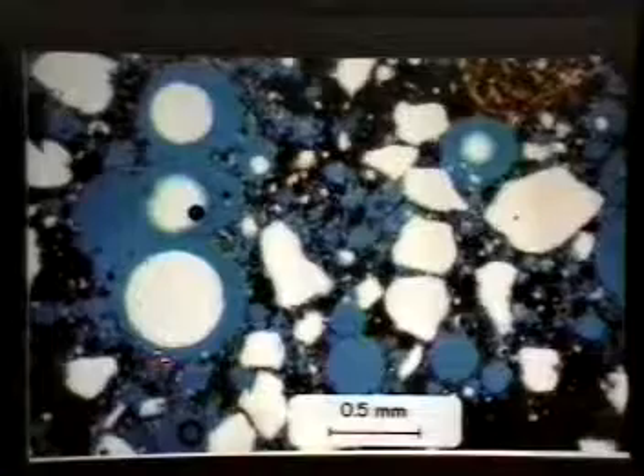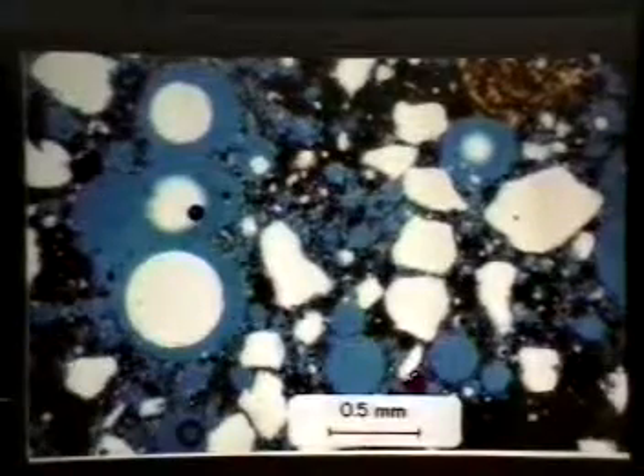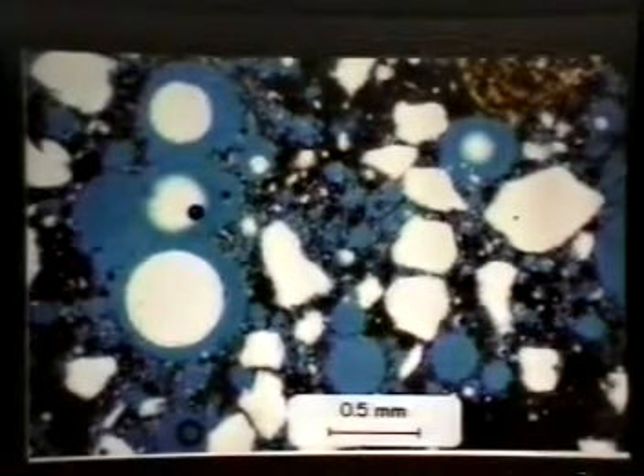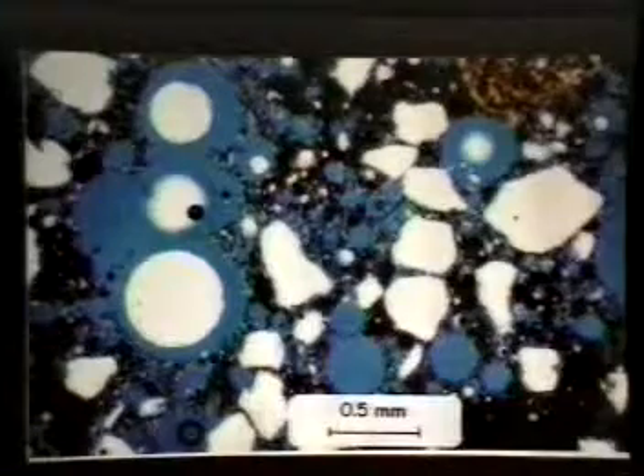The problem arises when you have agglomeration of all these, and high air content in the concrete. It reduces the strength quite drastically. Additionally, when you have concentration of air voids at the aggregate interface, this is aggregate, it reduces the bond strength of the paste aggregate bonding.